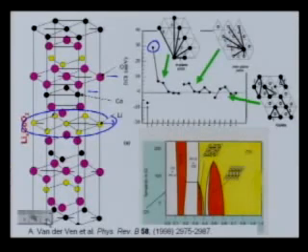And again, let me stress that these ECI are effective interactions. If you look at the first neighbor, it's only 30 millielectron volt. To give you an idea, those first neighbor distances in the lithium plane are about 3 angstrom. If you evaluated the electrostatics of a +1 charge and a +1 charge over 3 angstrom, you'd get something that's close to an electron volt.